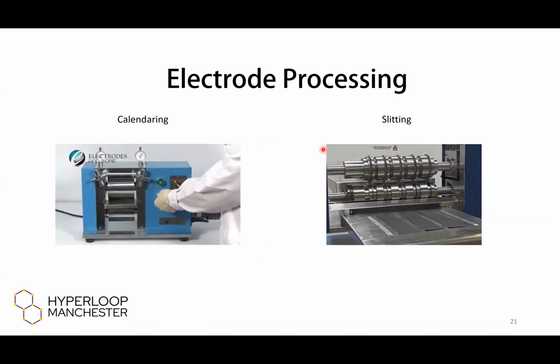So speaking of those next steps, the main ones really are the calendaring and the slitting. Calendaring is kind of, as it suggests, just compacting the materials down between two rollers typically. These can be heated or just at room temperature, depending on what sort of rheological properties it has. So like the viscosity, not really the viscosity, but the performance of the material, the binders maybe that you've used inside. And then after you've calendared them, you can slit the materials down to the shapes and sizes that you want that'll be suitable for the electrodes or the batteries that they're going into.